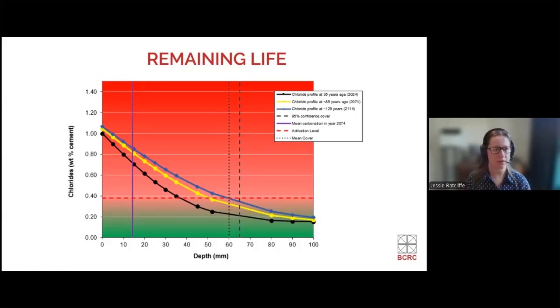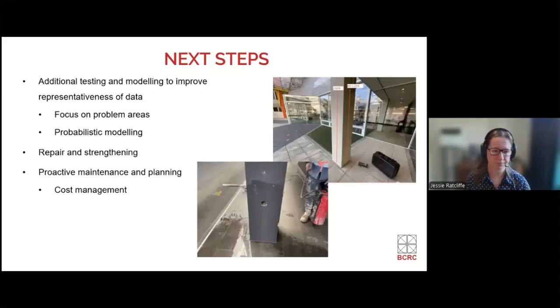We might be considering that in localized regions where we maybe found a higher bar with less cover, we could be considering some issues. And then our service life ends when the structure is 125 years old, 90 years on, where it intersects our average cover. So what do we use this data for?